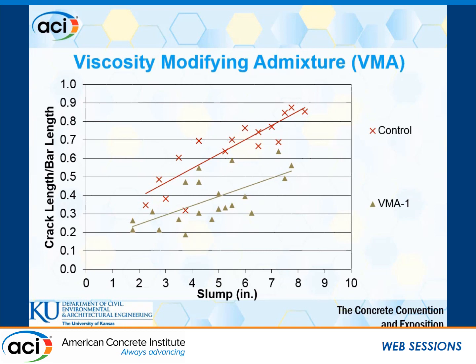The second technology is viscosity modifying admixture (VMA). When you add VMA to concrete, when the concrete is static — such as sitting in the form hardening or during a slump test — it behaves like a low slump concrete, giving you the benefits of less bleeding and less segregation. When you're working the concrete — pumping or finishing — it behaves like a high slump concrete, giving you high workability and pumpability. When we add VMA to the mix, we see a moderate reduction in settlement cracking length. However, if you want the workability of a six-inch mix with VMA, you can get away with a two- or three-inch slump concrete — making VMA a very promising technology for reducing settlement cracking.